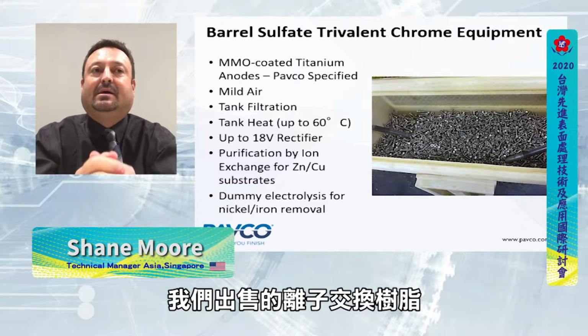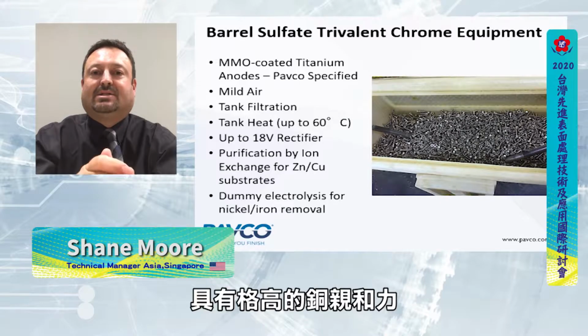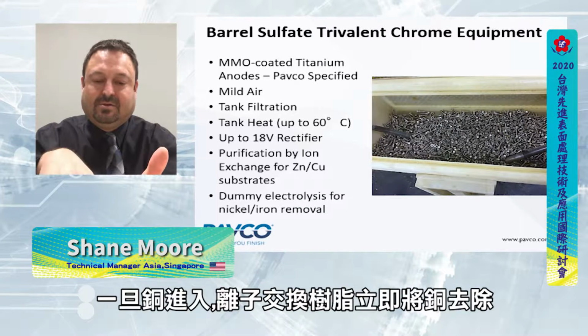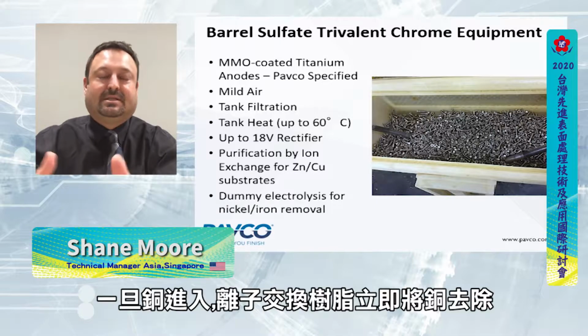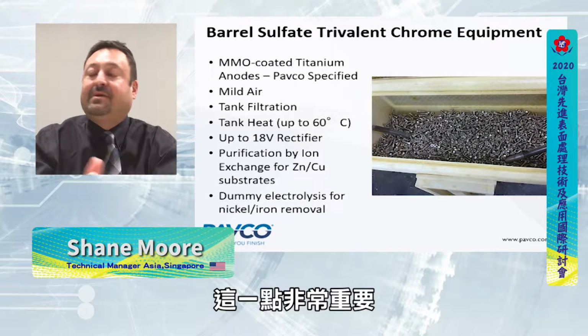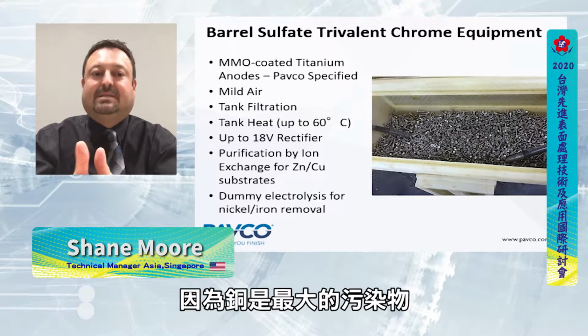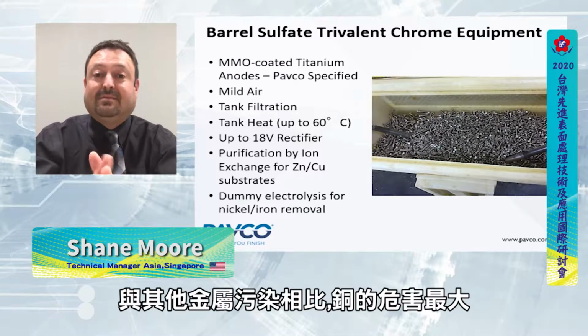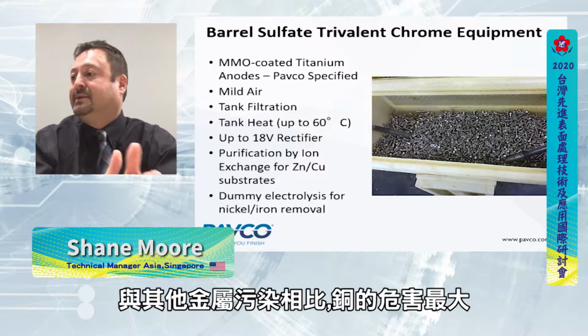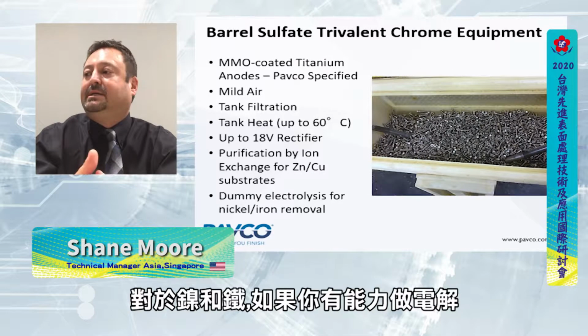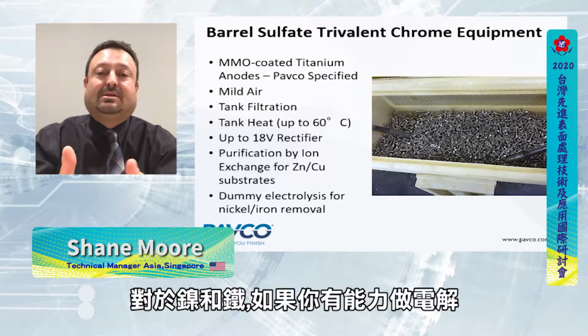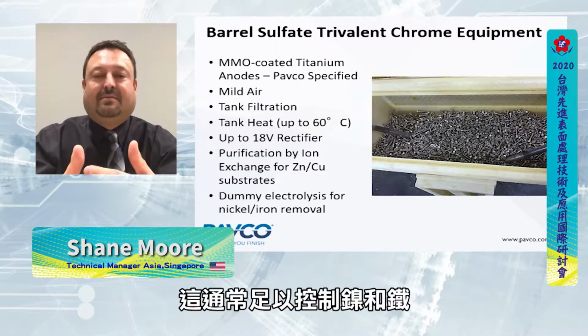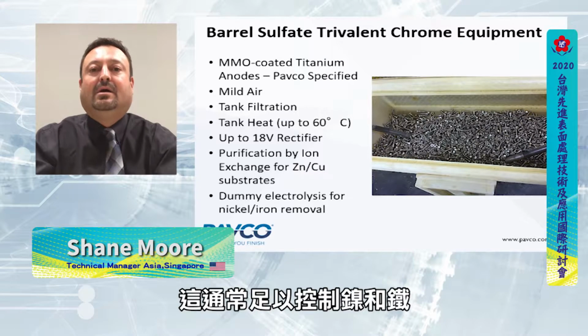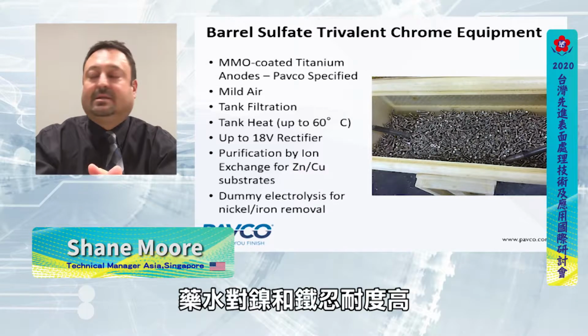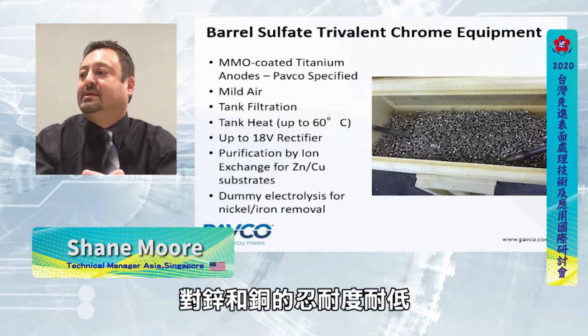The good thing about the ion exchange resin that we sell is that it has the highest affinity for copper. As soon as the copper is introduced into the bath, the ion exchange resin removes it immediately. This is very important because copper is the biggest contaminant, and the bath has the most sensitivity to copper than any of the other metallic contamination. For nickel and iron, as long as you have the ability to dummy electrolyze scrap parts or whatever, that's usually enough to contain them, because this bath is very tolerant for nickel and iron, but not very much for zinc and copper substrates.